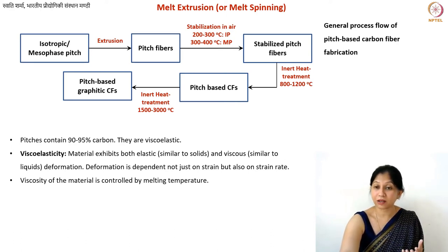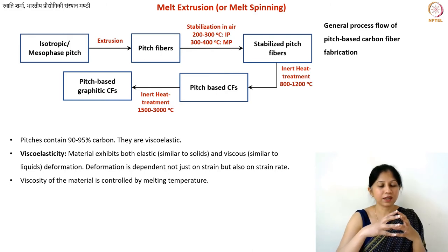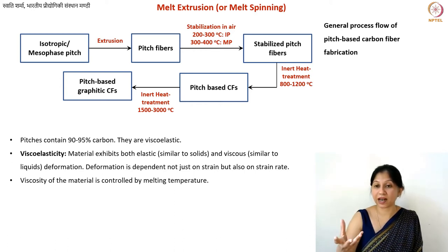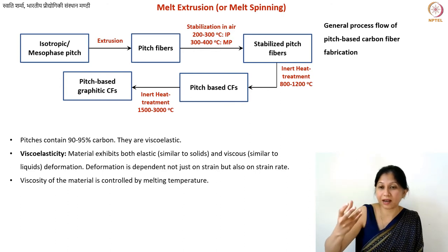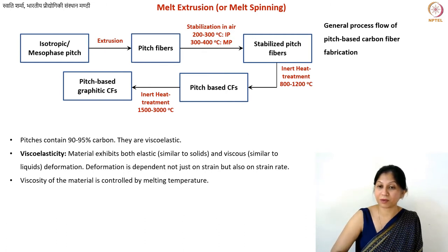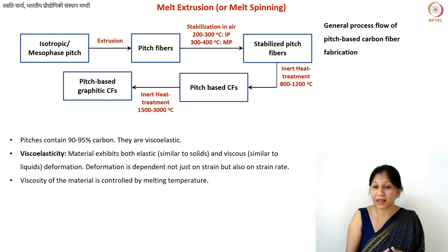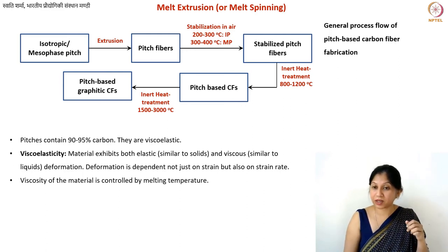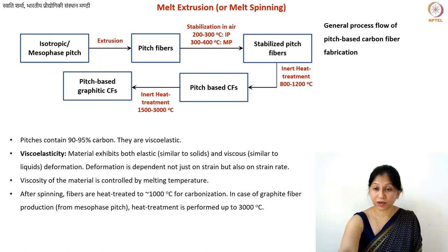In melt spinning, you also control viscosity by the melting temperature because you want an optimum viscosity for forming fibers and controlling fiber diameter. If your material has water-like properties, you cannot pull fibers. If it is slightly more viscous than water, you can pull very thin fibers — but their aspect ratio and minimum achievable diameter need to be optimized. If it is very viscous like honey, you can pull fibers, but the minimum diameter may be limited.